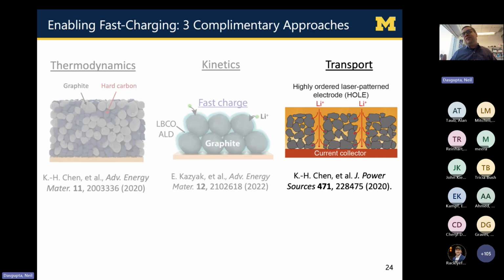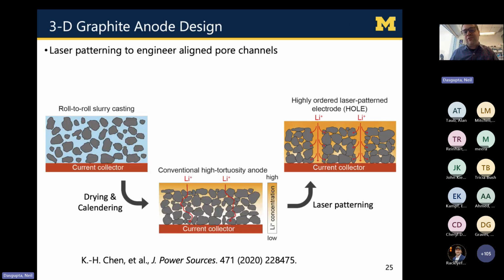So let me start with transport, because mass transport is one of the obvious ones, right? As I showed you earlier in that cross-sectional image, when you try to charge the battery too fast, it's difficult to get the lithium in and out. You over-lithiate the top surface, you have this lithium plating that occurs, and you didn't really take advantage of a lot of that graphite deeper in the electrode. So here our strategy was, could we introduce channels that allow for very rapid diffusion or transport of lithium deeper into these thick electrodes? And could we do this in a manner that doesn't sacrifice energy density?